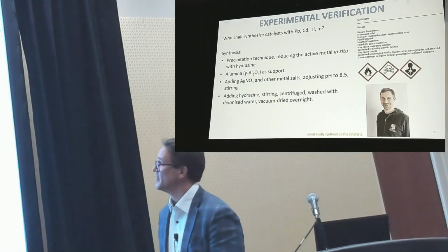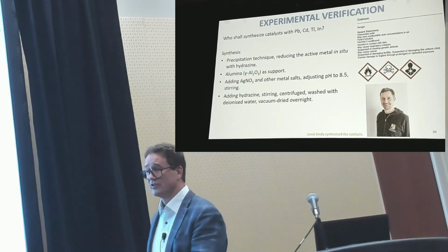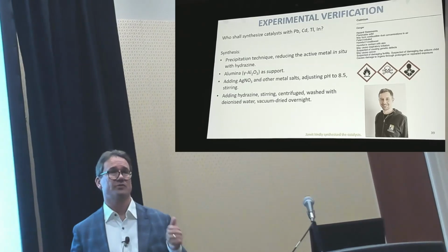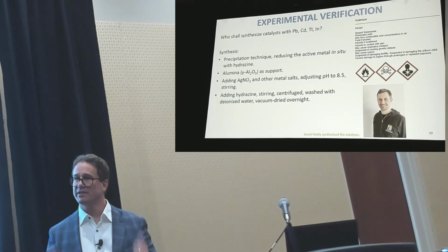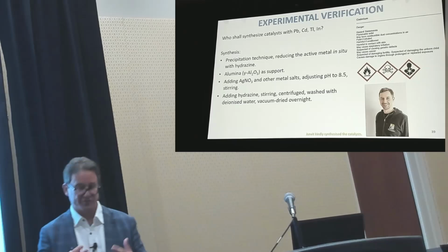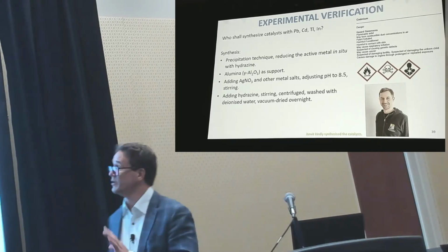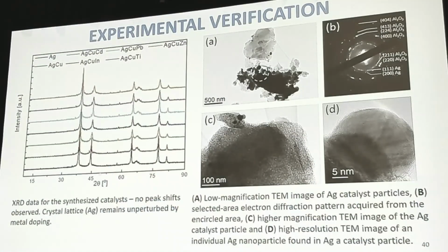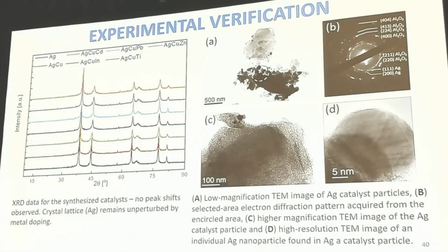So this is super impressive. We had a collaboration where they could synthesize this, and the main focus in this part was that it should be scalable. Whatever candidate we have, it should be absolutely scalable, so no strange methods of doing it. So we went into the lab, synthesized it, and it's really good. Here you have the XRD spectra, and you can see that we form crystallines. We do the SEM and TEM, and you see that it's a crystalline surface, it's metallic in phase.